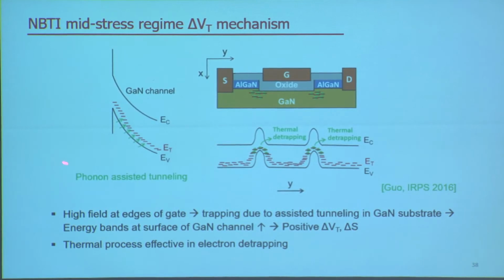With this assisted tunneling, it will lift off the energy band at this region, and they show up as an effective increase of doping level. And as a result, you will see a positive VT shift. After we remove the stress, because the energy barrier here for the electron is low, thermal detrapping is effective for the electron to get released. Therefore, this is a recoverable process.